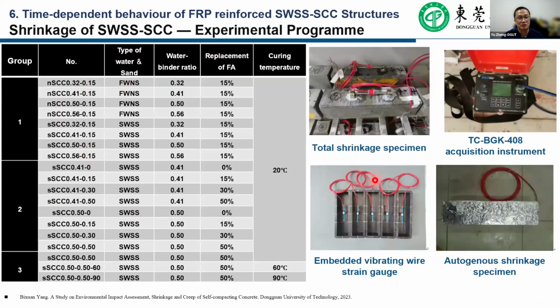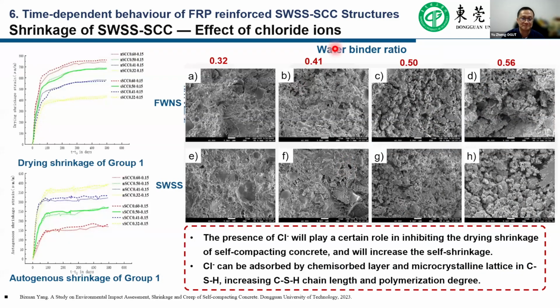In the first part, we investigated the total shrinkage, including the autogenous and drying shrinkage of these concrete materials. We can find in these figures that, when the other parameters are the same, because seawater and sea sand were used in this study, increasing the chloride ions played a certain role in reducing the drying shrinkage and increasing the autogenous shrinkage of this seawater and sea sand concrete.